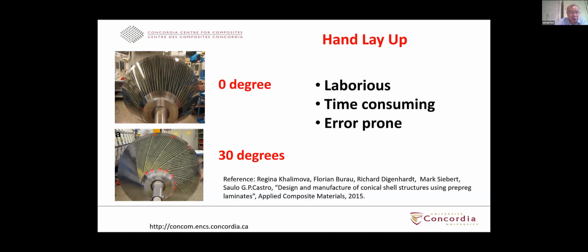Okay. So in this case, you're doing the hand layup. You have strips of the composite and you lay them on top of the mantle. So in this case you can do that at 0 degrees. For example, you can have a strip of 0 degree, but you have the situation of lap and gap. In the sense, you have some location where you cannot really cover the surface, and you have to cut some kind of partial fiber to place over the surface.